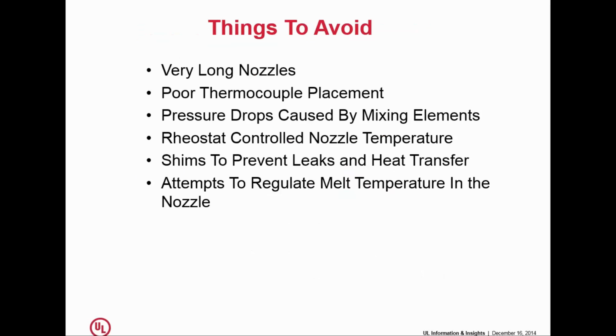Other things to avoid, very long nozzles. This gets into the whole thing of where the thermocouple is. Recently I worked on a project where the nozzle was so long that there was a temperature gradient from the back of the nozzle to the front of the nozzle of over 100 degrees Fahrenheit. The temperature at the back of the nozzle was actually below the crystalline melting point of the material. It actually wasn't even hot enough to melt the resin.